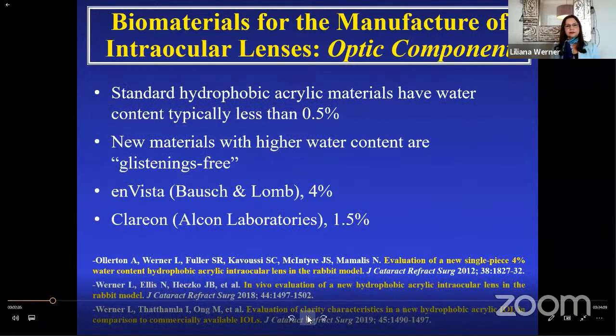Standard hydrophobic acrylic lenses usually have water contents that are below 0.5%. However, new hydrophobic acrylic materials with higher water contents became available in the markets some years ago, and they are considered to be glistenings-free. We will talk about glistenings a little bit later. Some examples of lenses manufactured from these materials are the Envista from Bausch & Lomb, with a water content of approximately 4%, and the Clareon from Alcon, with a water content of approximately 1.5%.